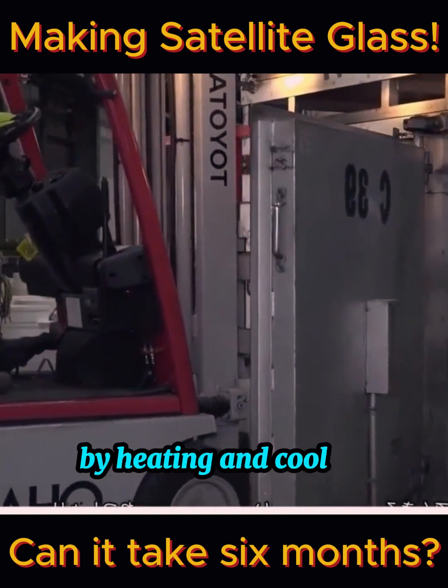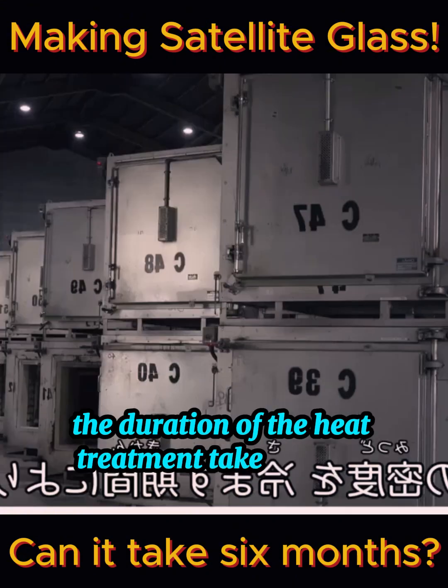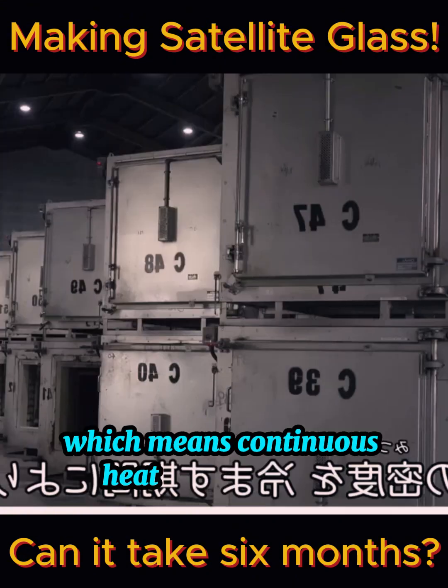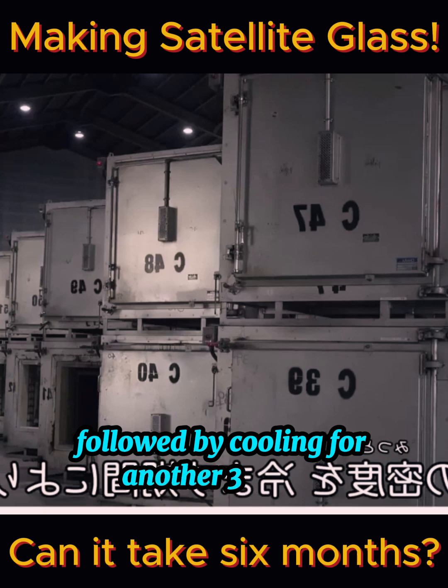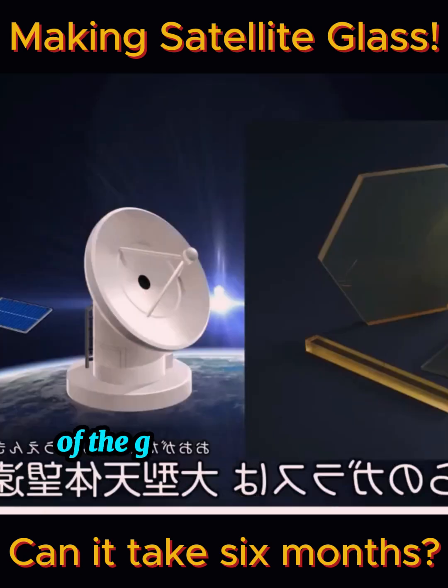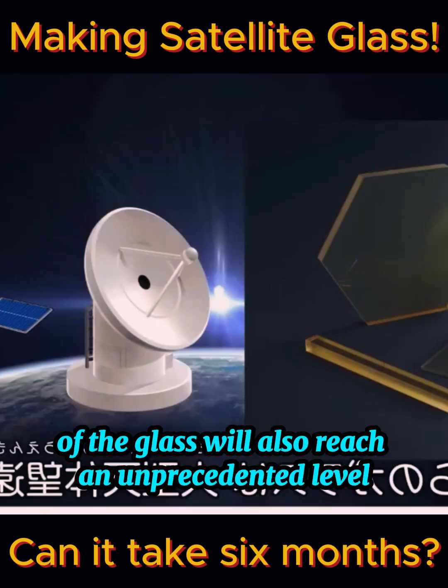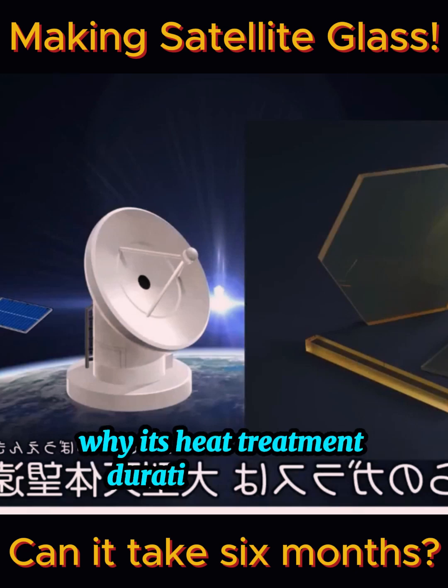By heating and cooling, the internal stress of the glass can be relieved, thereby reducing the risk of shattering in special scenarios. However, the duration of the heat treatment takes a full 3 months, which means continuous heating for 3 months, followed by cooling for another 3 months. In addition, the refractive index of the glass will also reach an unprecedented level. Now let's take a look at why its heat treatment duration is so long.